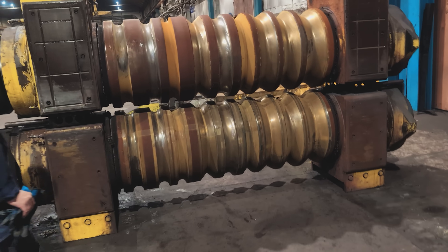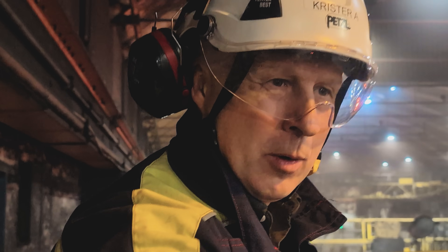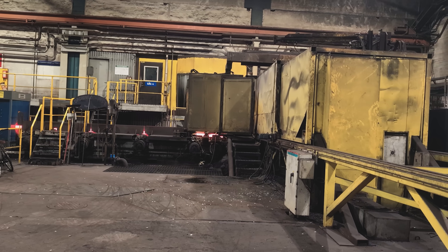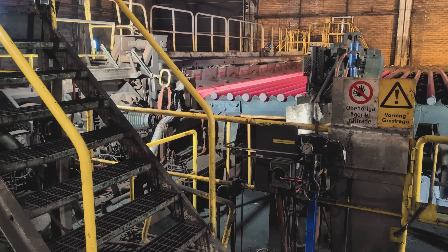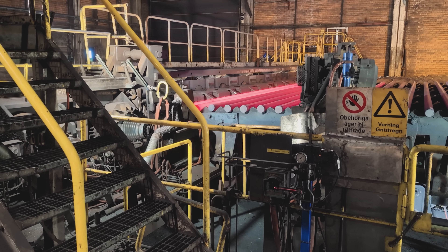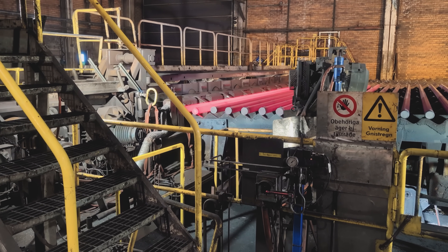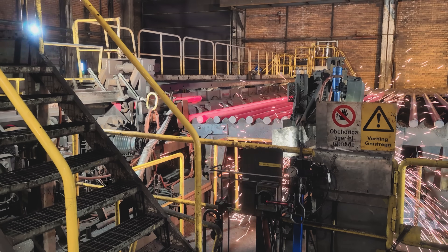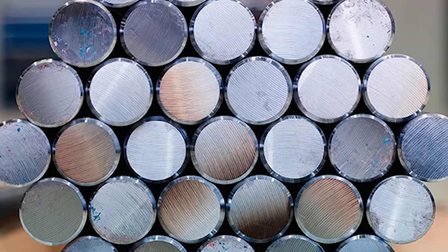Main products will be further processed in our other facilities, like tube mills, ring rolling, and bar peeling machines. But here we produce black bars. We have different rollers for different sizes. After rolling, we cut away the ends of the bar through a hot shear, removing the top of the ingot to clear it from surface defects. The bars are then cut and end up on the cooling bed, where we mark and grind the ends to remove burrs and apply the heat number.